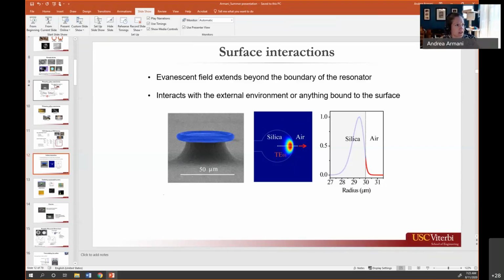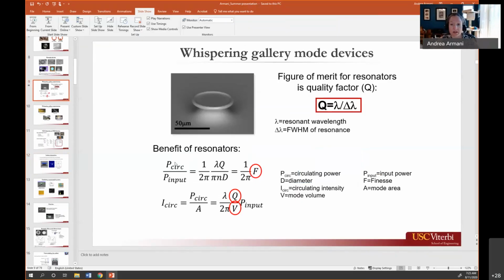And the reason why whispering gallery modes, as well as other types of resonators like photonic crystals, are able to access nonlinearities is because if you look at this equation, the circulating power is proportional to the quality factor. If you have a quality factor of 10 to the 8th and you put in a milliwatt of power, you're going to get your input power amplified by 10 to the 8th. So you're going to get a significant amplification of even a very low input power.